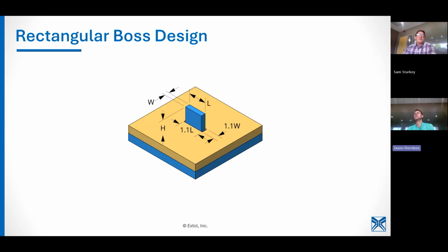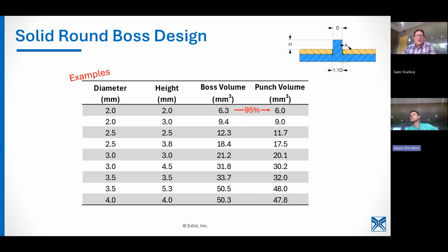So we do design to about 95% of the CAD. So, kind of back to that point, if you start to get your bosses varying to the high side, you can start to overfill that cavity and it has nowhere to go but out. And so in severe cases, if you're over driving, you haven't set up your hard stop specifically where it needs to be, and you start over driving, you certainly can get sticking, and then once it starts, it's hard to stop.